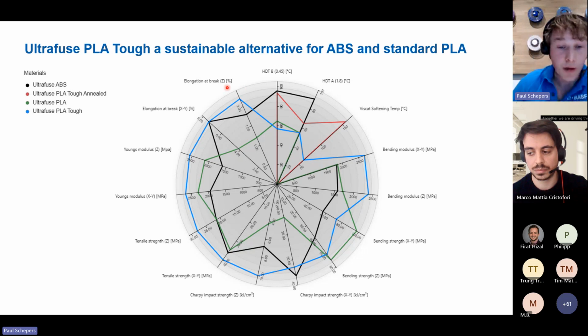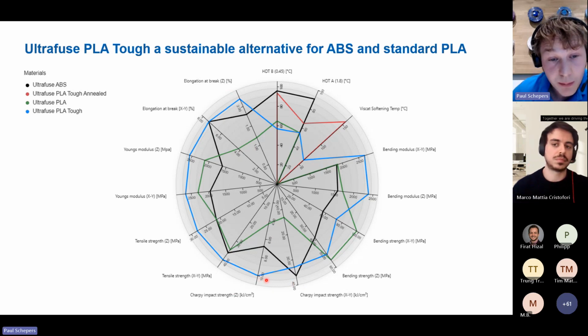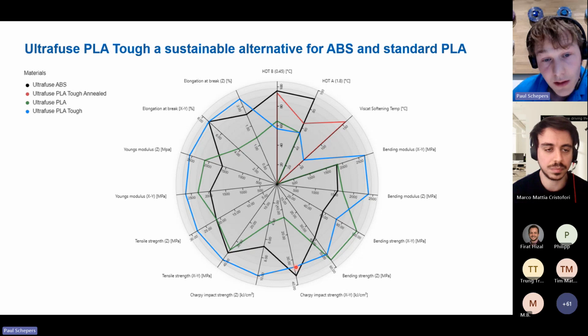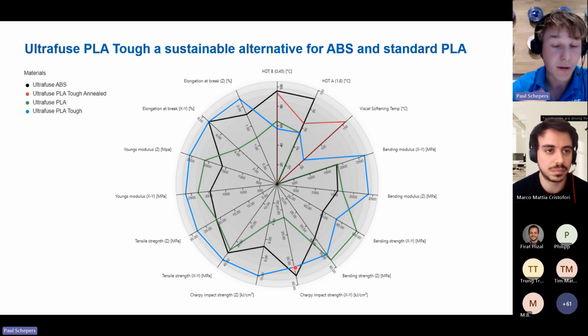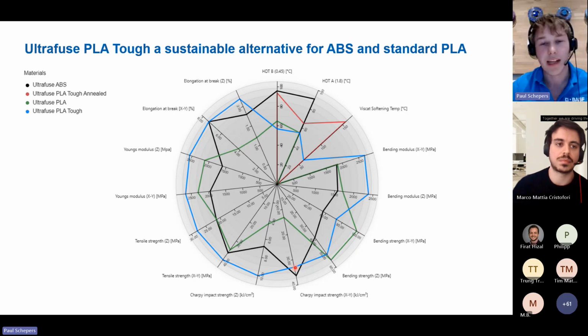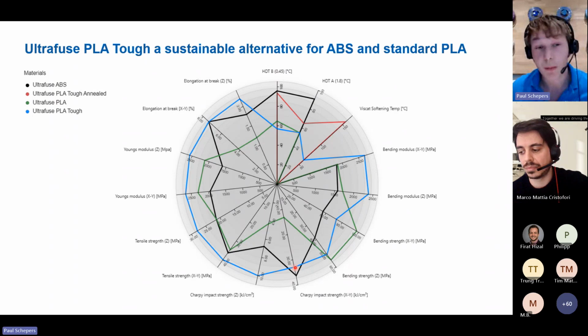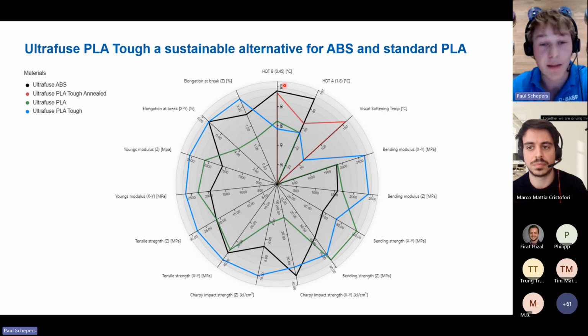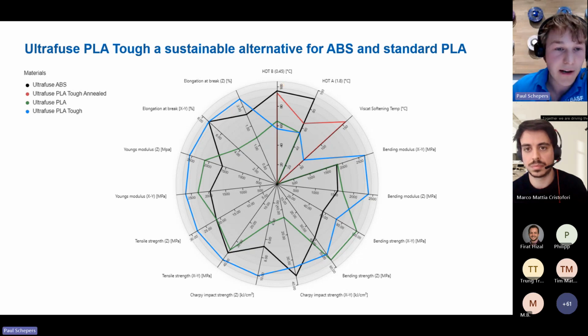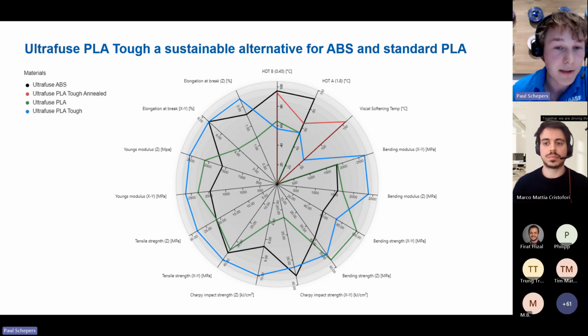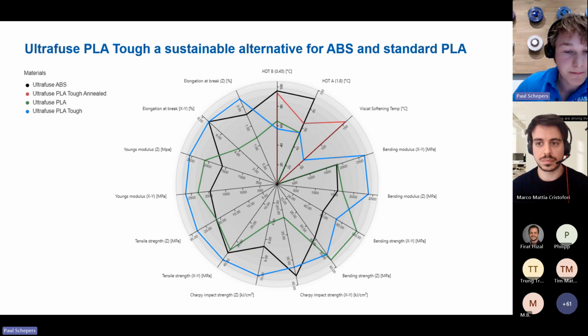If you look at the impact tests, you see that it is also outperforming ABS. Sometimes it's quite close. But if you need heat resistance in general, then always go for an ABS material. However, you can compensate by annealing it. So the PLA Tough, if you anneal it, you enhance the superpowers. And that is reflected in this area. Normally in blue, you see the heat resistance of the material over here. And we can enhance these properties by annealing it. Then you see that it increases the thermal resistance, so it comes quite close to an ABS material. And of course, it's stronger than an ABS, as already mentioned before.